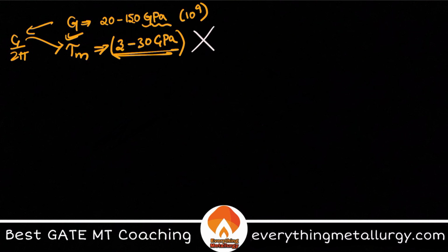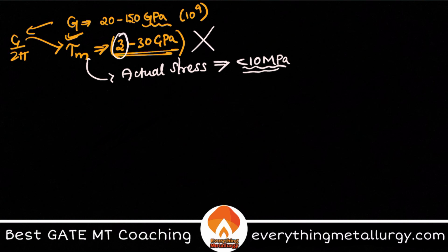But experimentally it is not at all this much stress. If you do the experiment, the actual shear stress values for plastic flow are less than 10 MPa. So you see the difference. Here the lower range is how much? 3 GPa, that is 3000 MPa, correct? Giga is 10 to the power 9, mega is 10 to the power 6. So the lower range from the theoretical calculation is 3000 MPa.